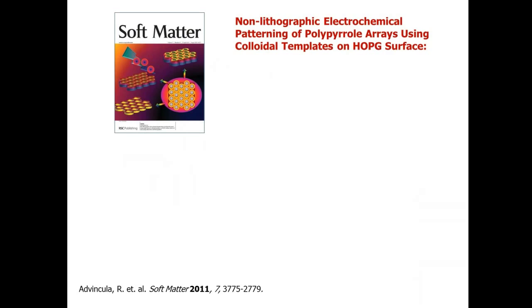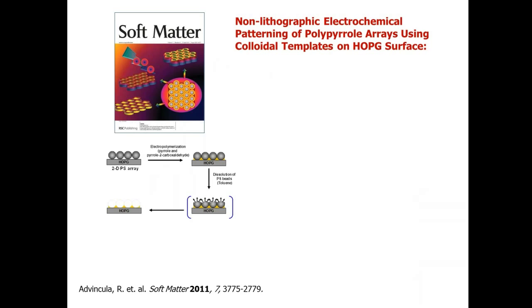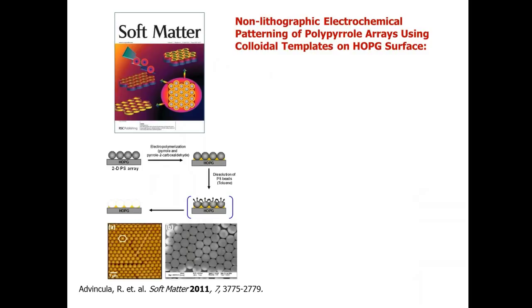We developed back in 2011 a method which we call templating using colloidal particles. As shown here, we can make an array of colloidal particles of 500 nanometer spherical polystyrene made from emulsion polymerization. When you layer them two-dimensionally, the material will deposit on the interstitial spaces of these colloids, forming a pattern which can be developed by removing the polystyrene particles.